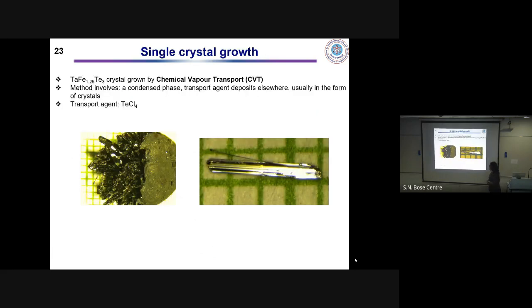We first tried to grow the TaFe1.25Te3 compound using the chemical vapor transport method. We tried to grow this using both kinds of transport agent, iodine and TeCl4. However, with iodine we were not able to grow single crystals. TeCl4 gave us good single crystals, but they were needle-like. They were long enough to make contact, but the width was very small, so it is very difficult to make contact in this system, especially when we cleave it.